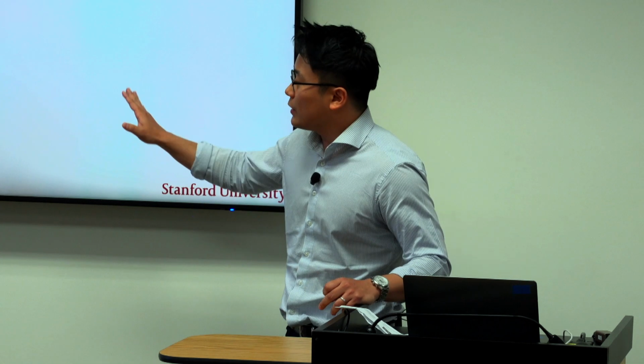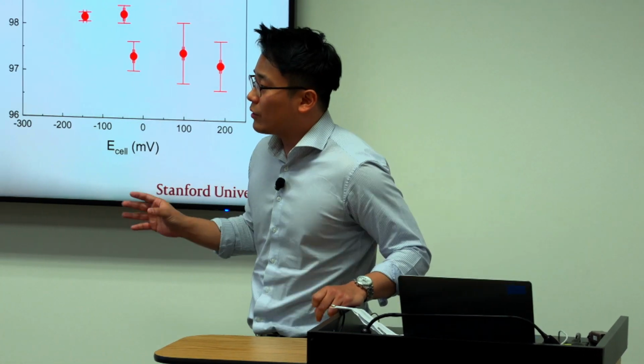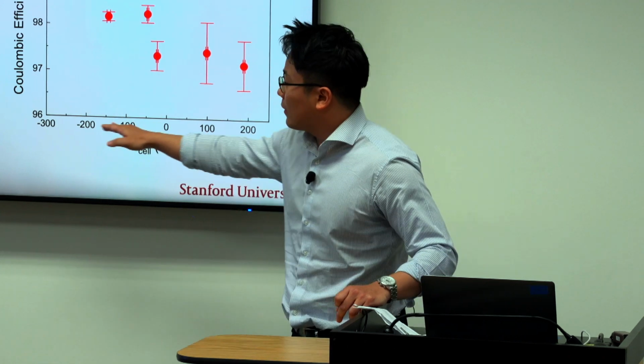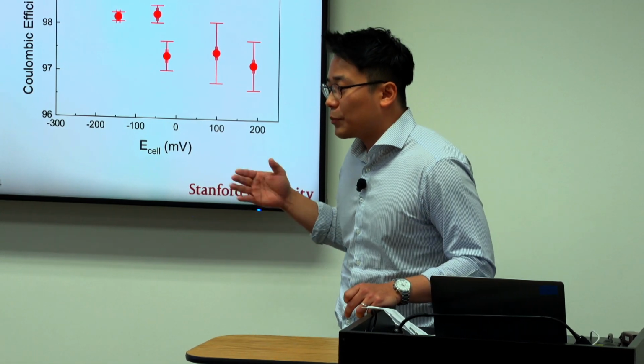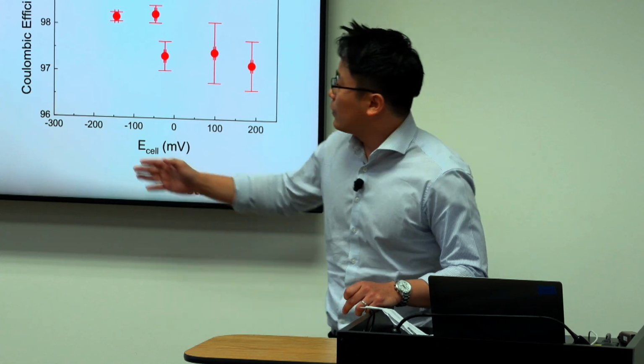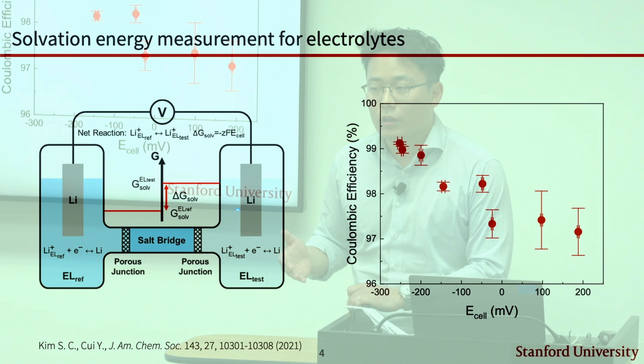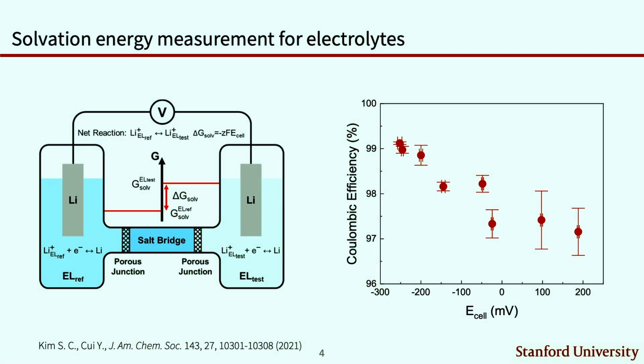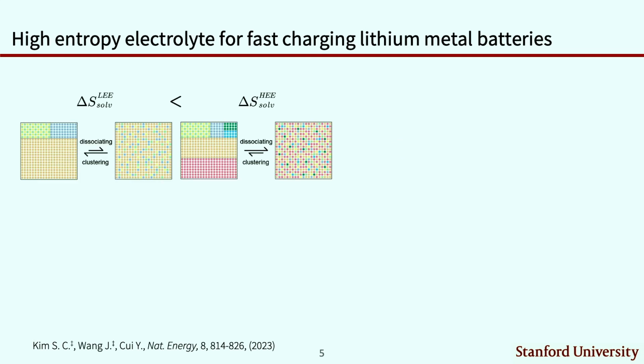I won't go into all the details here, but using a relatively simple electrochemical setup, we can actually probe the solvation energies of different electrolytes. And one really key, interesting finding that we had was this: on the bottom axis, we have the cell potential, or essentially the solvation energies. And on the vertical axis, we have the Coulombic efficiency, which is a measure of essentially the cycle life of your battery. And we have this nice correlation, which tells us that to improve the Coulombic efficiency of your batteries, you want to have weaker solvation. Essentially, the binding between solvents and lithium ions, we want to be weaker. So that's one piece of my research.